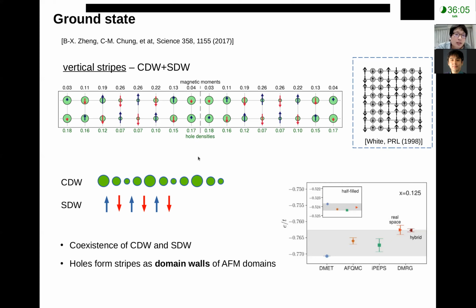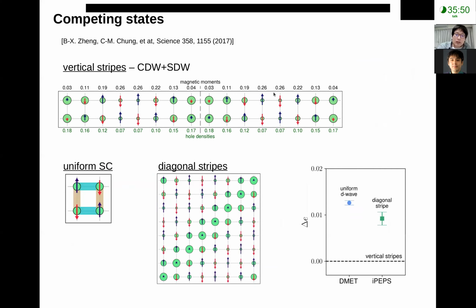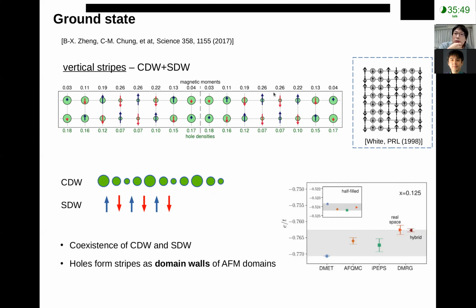And this stripe, or this hole, plays as a domain wall for the antiferromagnetic domain. You see the antiferromagnetic pattern actually flip the spin when it crosses a stripe. So this spatial coexistence of charge density wave and spin density wave together, we call a stripe order.